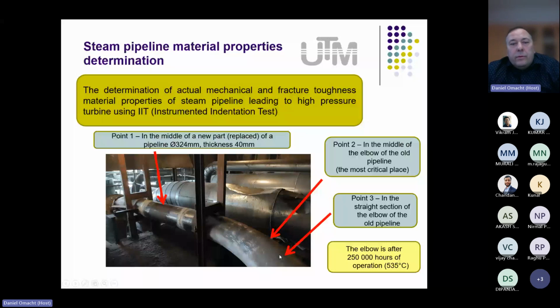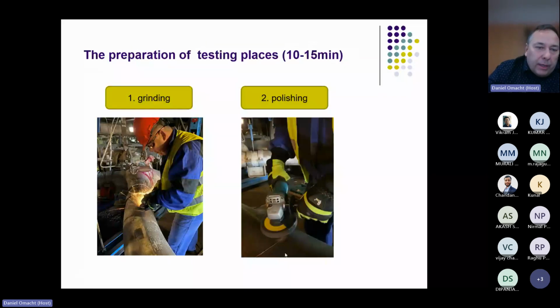As a first step, it was necessary to prepare the surface. For this, we used a standard grinder, and as the second step, we did it in 4 steps, but it is not necessary to tell you all the details. But the second step, we can say, we used a polishing wheel.